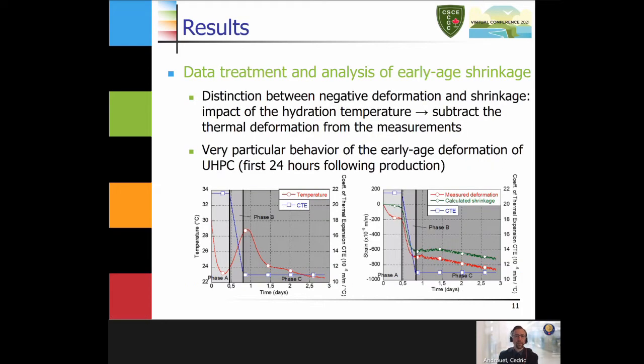When we have a look at the results, we need first to make a distinction between the negative deformation we measure with the sensor and the shrinkage itself. Why? Because we have an impact of the hydration temperature. Here on the left is the temperature we measured in the cylinder with the thermocouple. You see that we have quite a high hydration temperature in the mix. This leads to thermal deformation, so we need to take this thermal deformation into account. If you look at the right, in red is what is measured by the sensor in terms of deformation, and in green is what we call the calculated shrinkage. The difference between the two is simply the thermal deformation.